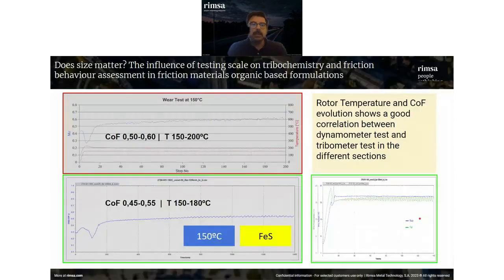Okay, and if we go to the detail of how this coefficient of friction of the friction material and the rotor evolves, we will compare here the results in red of the full-scale dyno with, in green, the results of the coefficient of friction evolution on the tribometer. You can see here the comparison at 150 degrees with iron sulfide. We start here at the 200 stops, and here what you see is the coefficient of friction line in the dynamometer, and here is the evolution of the coefficient of friction line in the tribometer. So you see this particular drop in coefficient of friction is being replicated in the dynamometer and the tribometer. Here, these lines are the evolution of the temperature.